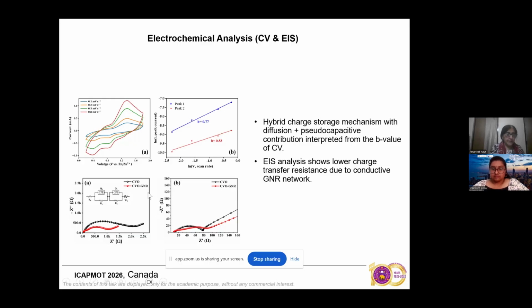And the CV curves, because we have done cyclic voltammetry at different scan rates. Even at the scan rate of 0.1 millivolt per second, it shows the multiple intercalation and deintercalation of zinc ions in the structure, which can be explained with two pairs of redox peaks. One is observed at 0.851 volts and the other at 1.36 volts. And the reduction peaks are observed at 0.8 and 0.396 volts, which represent the two-stage redox transition from V5+ to V4+ and then V4+ to V3+.